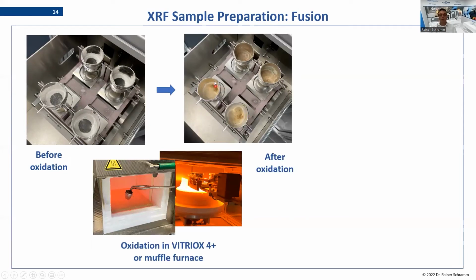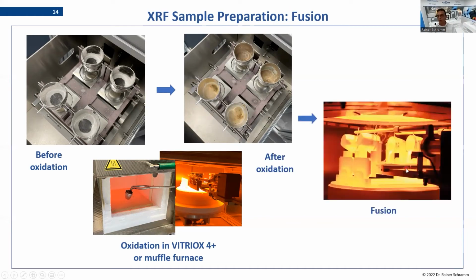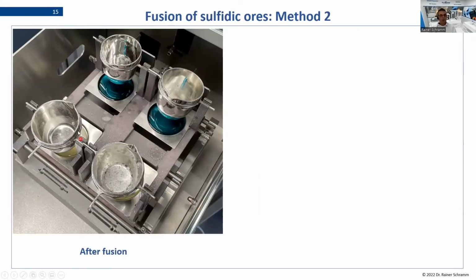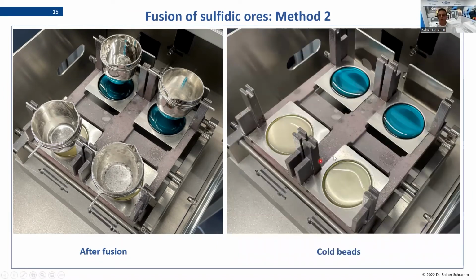And when it comes out, you see the flux is nearly untouched because temperature was too low, no contact with the platinumware, so you are safe. And the sample is really oxidized and on top. And now it's time to put it into a fusion machine to cast the glass in the end. When it comes back, we will have our empty crucibles, which because of the non-wetting agents, are practically empty. And if we take them away, you see the glass, in this case, 2 copper ores and 2 zinc ores, nicely formed with a good recipe.